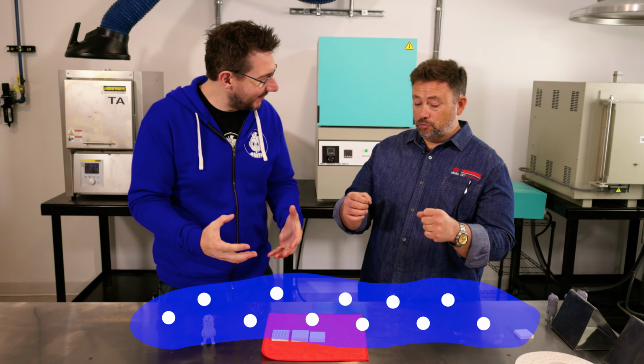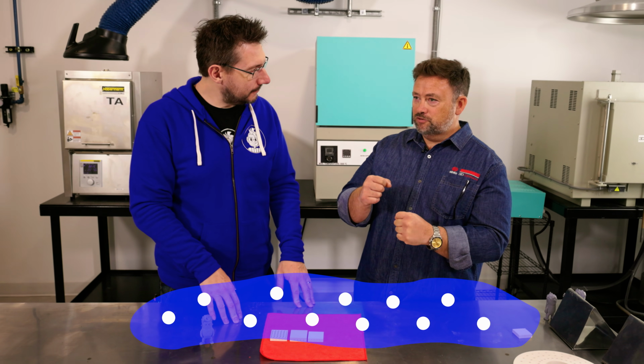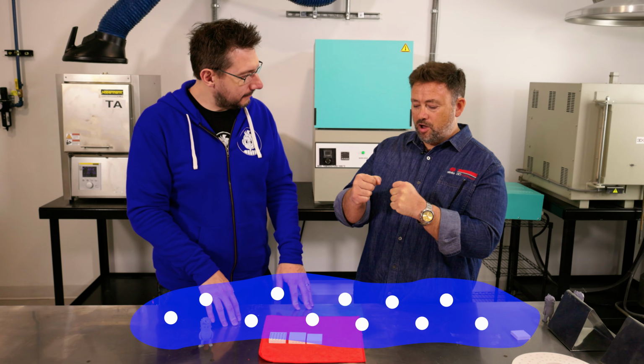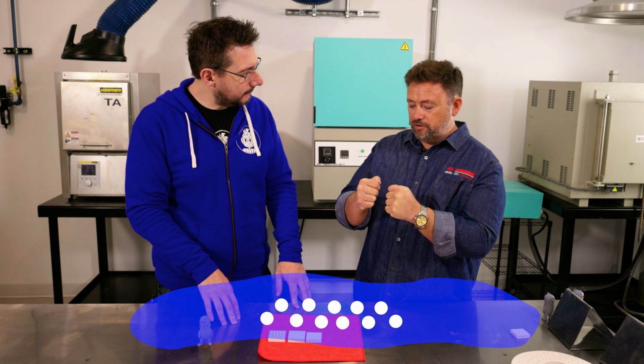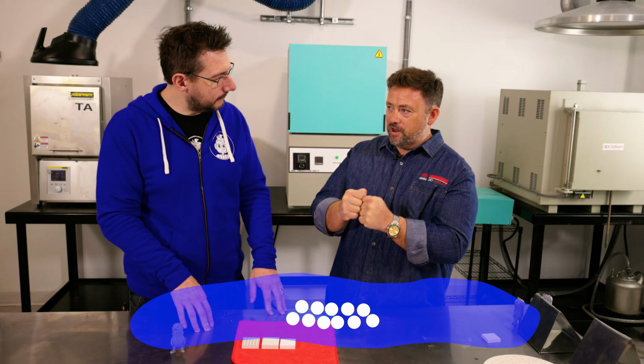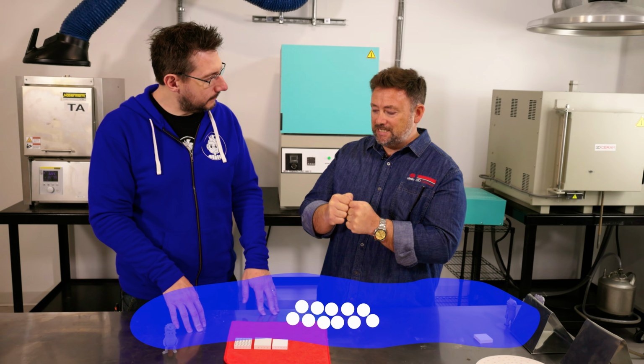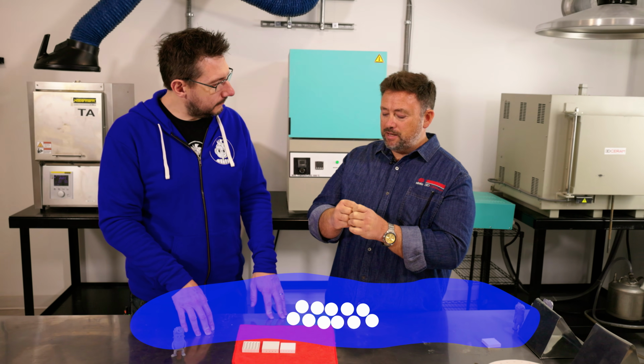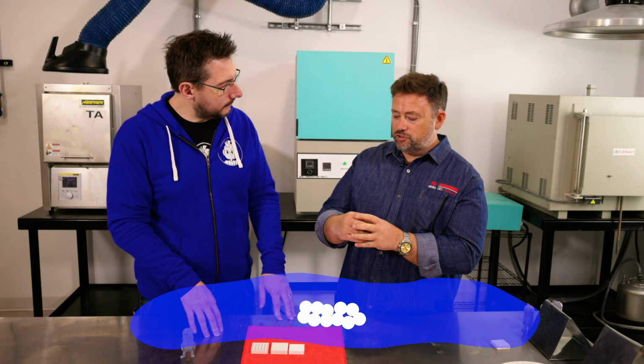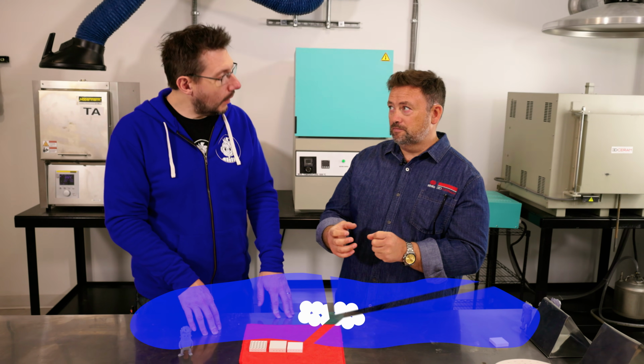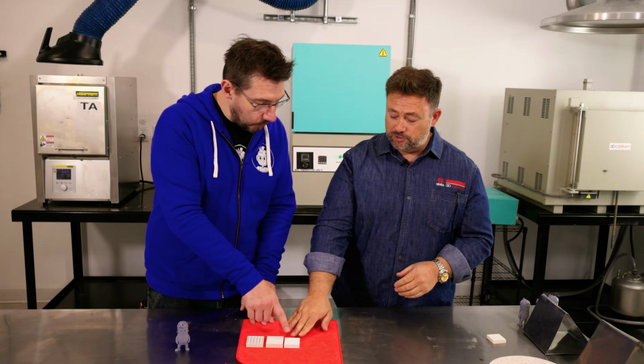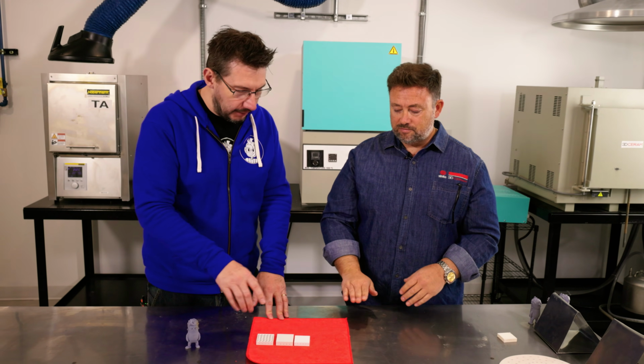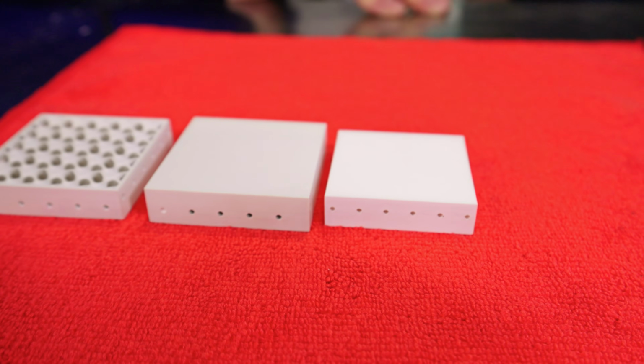It removed it, but in that process of heating it to remove it, it shrunk it. Right, so the little grains of ceramic that are stuck inside of the resin goo start coming closer and closer together until they're touching. Once they're touching, then you've got a pretty nicely fused and fully sintered ceramic. If you start bonding the molecules or the grains together, you start becoming crystalline and then it becomes too brittle. And you don't want that. So you want it just to be grains close together. That's kind of the basics of ceramic. So that's what we're seeing here. It's debound. We have all the resin out. This is a ceramic piece.